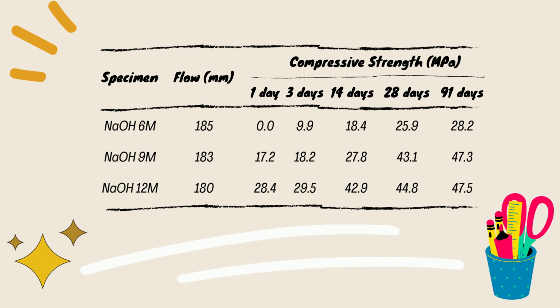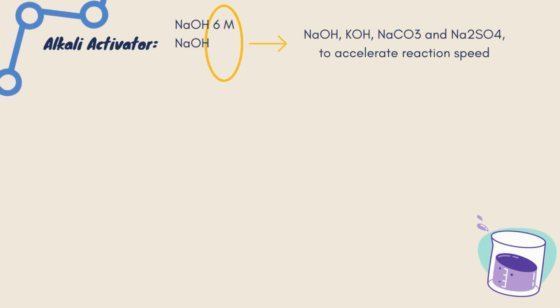For the compressive strength, the geopolymerization of fly ash and the strength are increasing from day 1 until day 91. The specimen with 12 mole concentration has the highest strength, 47 megapascal, which is known as high strength concrete, compared to 6 mole and 9 mole concentrations of sodium hydroxide. This verifies the potential of fly ash as a replacement for cement. However, this geopolymer concrete is more suitable for precast concrete because the compressive strength is developed at temperatures that exceed 60 degrees Celsius.